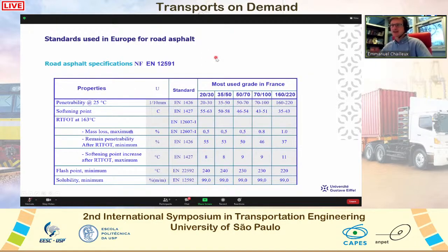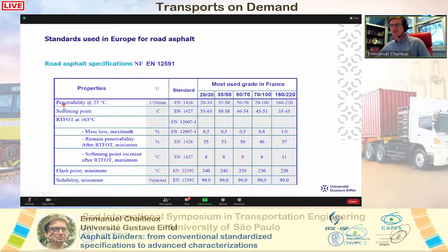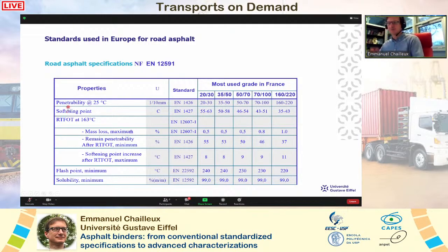So at the end, we have this type of table where road asphalt can be specified according to different grades. And you see that the properties needed to specify a road asphalt in Europe are just penetrability, softening point, and penetrability and softening point after aging by RTFOT. We also have the flash point and solubility, but they are very common properties. So the grade is defined by the penetrability.